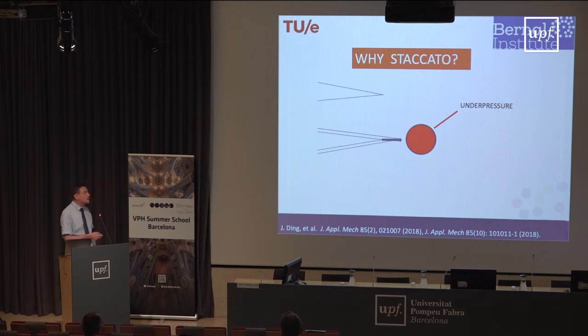Now the question: why is it staccato? What happens is that in poromechanics things are more complicated. In a solid, you have a crack. Ahead of the crack, the material is somehow torn apart. It needs to be torn apart because that is going to allow the crack to propagate. So you get a triaxial tensile state ahead of the crack. And this happens in poromechanics also, only it is the fluid which is under pressure.